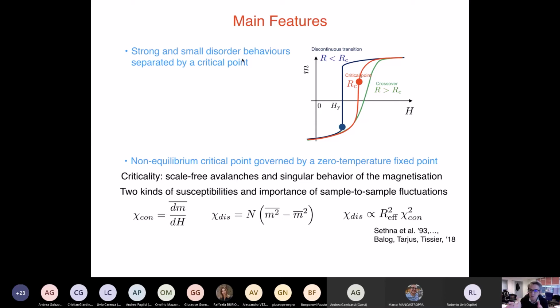And then, when you decrease the disorder, the curve becomes steeper and steeper, and at a certain point you have a critical point, in red, at a certain value of the disorder. If you go below this value RC of the disorder, then the magnetization has a kind of first order or discontinuous behavior, meaning that you follow the negative magnetization until a certain point, and then you jump discontinuously to another point, and then you follow the upper branch of the curve.